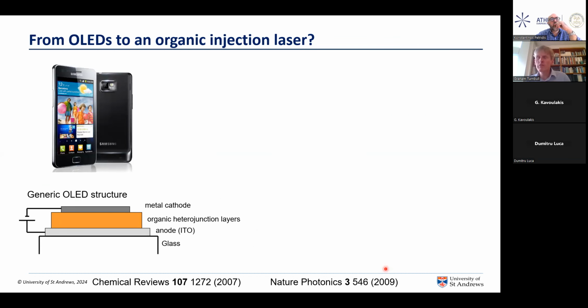So what about moving from an organic light emitting diode, which is a very successful technology, to an organic injection laser? To think about this, it's useful to first introduce the generic structure of an OLED. An OLED is a planar thin film device in which we have an organic layer or molecular layer, often actually multiple layers of different molecules serving different electrical transport and optical properties in the device. So we have a series of organic layers sandwiched between typically a metal electrode on one side that injects electrons and a transparent conducting electrode on the other side that injects holes into the device. The overall thickness of however many organic layers we have in this structure is typically in the order of 100 to 200 nanometers in total thickness. So they're very, very thin structures.